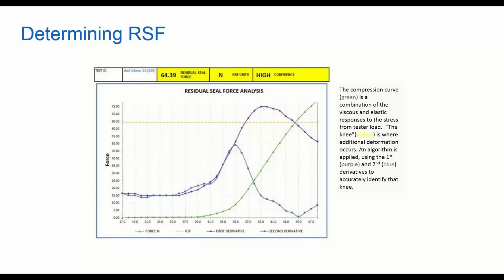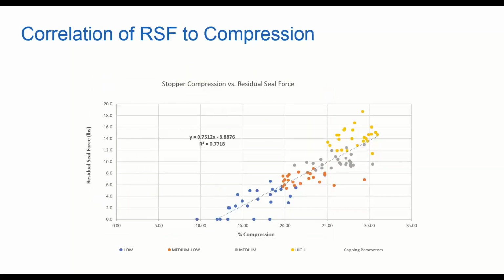To briefly summarize this, you take the first derivative of the stress strain curve and then the second derivative. The lighter blue line is the second derivative, the purple line is the first derivative. And what Ludwig shows is that the knee or residual seal force point corresponds directly with the first major peak or valley of the second derivative after the major peak of the first derivative. And his work, again, published a long time ago, peer-reviewed in the PDA journal, has demonstrated this very clearly, and this technique now has been used for close to 30 years, or over 30 years, I should say.